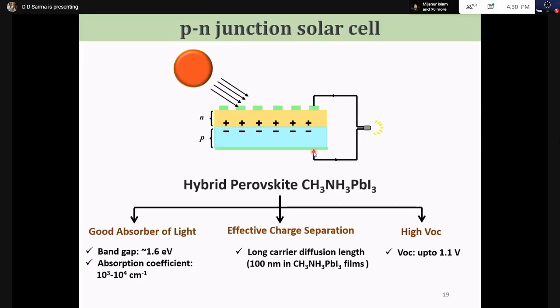In order to maximize the current, you can make the band gap very small, almost limiting to a zero band gap. All the photons will be absorbed, but then the voltage will go to zero, and so the power output will be zero. So you can see that in both the infinite band gap limit and the zero band gap limit, you get zero power output, which means the mathematical requirement is that the power must be maximum for an optimum value of the band gap in between. And that depends on the solar spectrum.